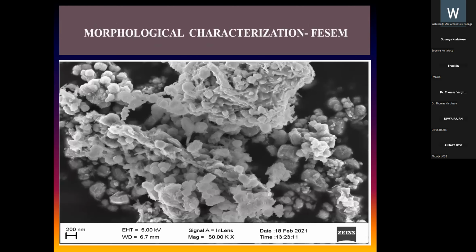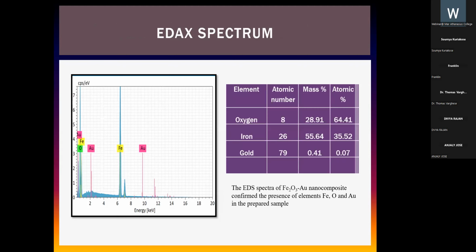Morphological characterization of the sample was done through FESEM. The image shows a nearly spherical, still non-uniform distribution of particles in the composite. EDAX spectrum also confirmed the presence of iron, oxygen, and gold in the prepared sample. After getting confirmation regarding the formation of nanocomposite, we have done the thermal diffusivity study.